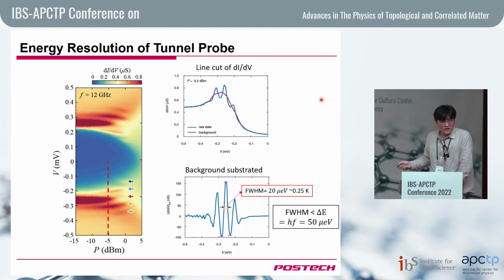So if I take a line cut here, you can see the original Andreev bound state and the replication of that Andreev bound state with the peak distance of 50 micro eV, as we expected with the frequency of 12 gigahertz. Okay? And at this point, I want to emphasize that this measurement was done with continuous shining microwave.